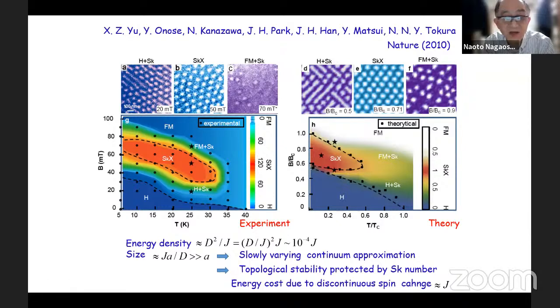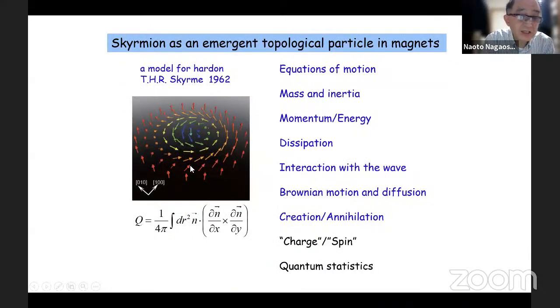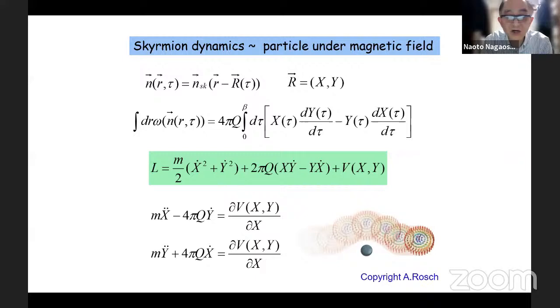And then the mapping from the real space to the sphere S2 becomes a continuum. And then the topological stability enters here, and the skyrmion number makes sense. But the energy cost due to the discontinuous spin change is of the order of J. So that's why this two energy scale hierarchy is quite important for the topological stability of the skyrmions. And as independent particles, you can talk about the equation of motion and the mass and the inertia and the momentum and dissipation, interaction with the spin wave and the Brownian motion and the creation and annihilation, et cetera. So this opens a very new field of noncollinear magnets in these 10 or 20 years.